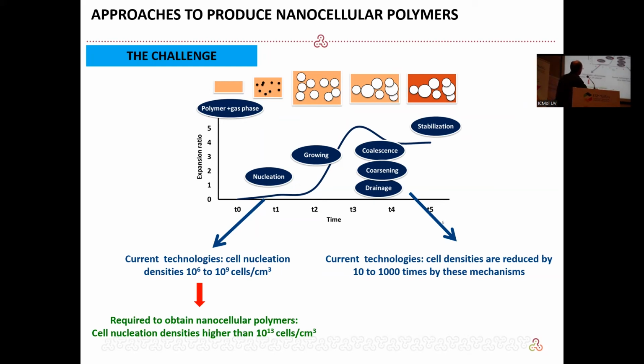If we go to the degeneration in current technologies, the degeneration ratios are between 10 and 1,000. So 1,000 means that you create 1,000 cells at the beginning of the process, and you finally have one. So 1,000 cells disappear and you just reach one. Of course, if you create a lot of cells, but they disappear in the process, at the end of the day, you don't have the nanocells.